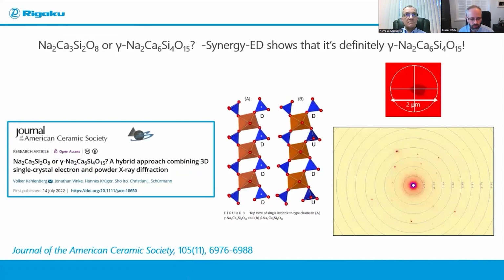So to excite your appetite a little bit about what's coming up in Robert's presentation, let me give you a few examples here. Here is an example where the uncertainty about which polymorph existed for this compound containing sodium, calcium, silicon, and oxygen could not be elucidated by X-ray diffraction. So there was nothing that people could get from X-ray diffraction because they couldn't grow proper crystals. However, using electron diffraction, they could identify which of the polymorphs they had. And I'll use this slide here to say that electron diffraction is really useful with inorganic and intermetallic compounds that can crystallize in several different phases with different stoichiometry and often as nanoparticles. And that's when electron diffraction can show its full force.